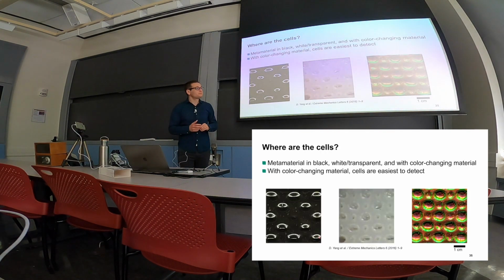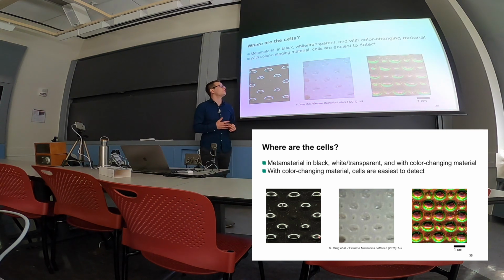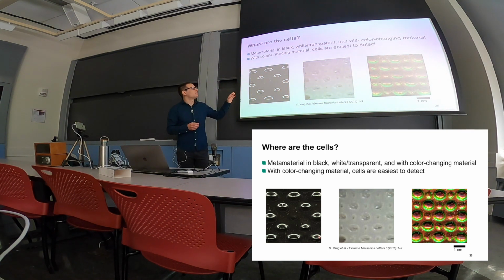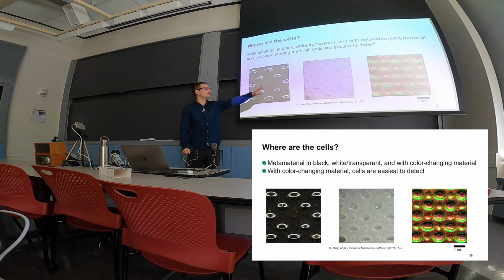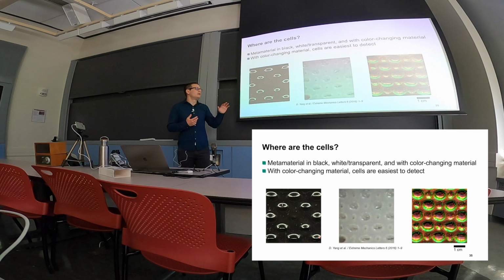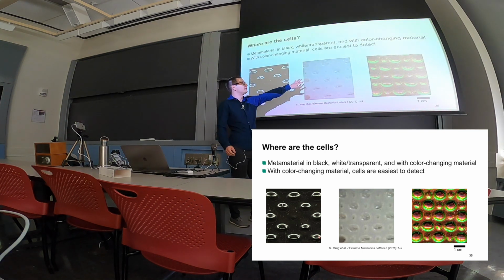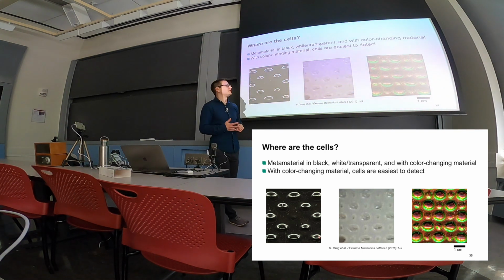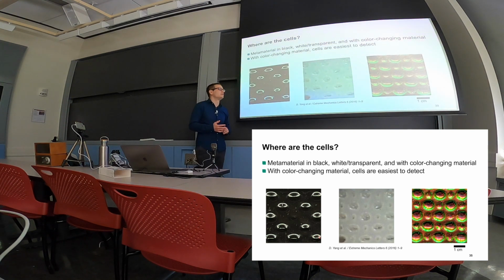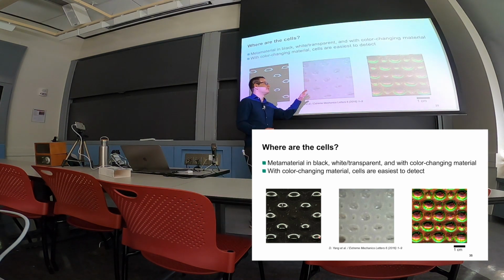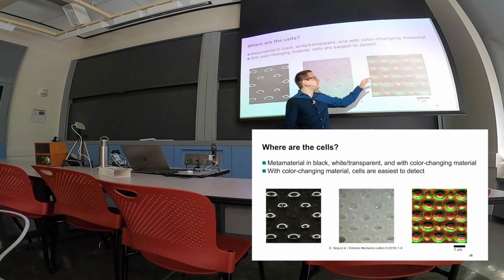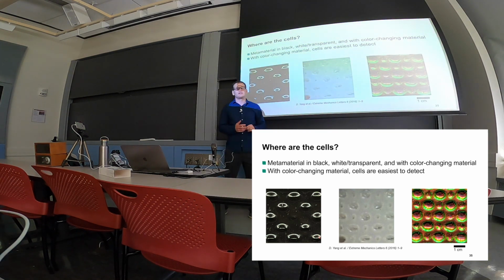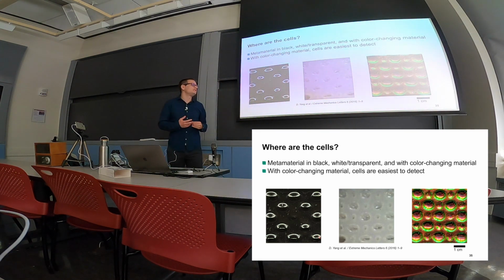And for the first point, I just needed to figure out how to apply the color-changing material to that die, and we can see that once I was able to do that, it was quite easy to detect where those cells are in the network. So once having the network with the same material as top and backing layer pigmented in black or without any pigments, we can see that the detection of those cells is quite difficult because the contrast between the background and the cells is not so high. But with applying the color-changing material, it was easy to detect those cells, and we even get more information because we see different colors on there that could be needed as well.